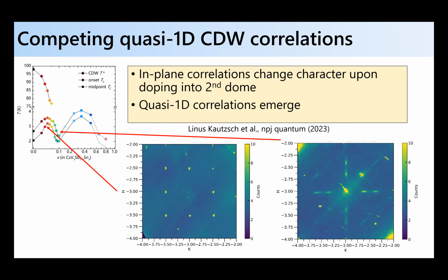And then what we can say is, okay, what happens to the charge correlations as you move across this phase diagram? If we're exploring competing instabilities that can be realized in the kagome band structure, what do the charge correlations do? So we can look at the peak of this first dome here in the charge density wave state, and if we look at X-ray scattering, this is the HK plane, so this is the AB plane of the kagome net. These peaks here are at superlattice positions that correspond to the 2x2 charge density wave order of the parent system, okay? So more or less in plane, the physics doesn't change from the parent compound to here. The charge correlations become a little more quasi-two-dimensional between the planes, but that's the main qualitative difference.